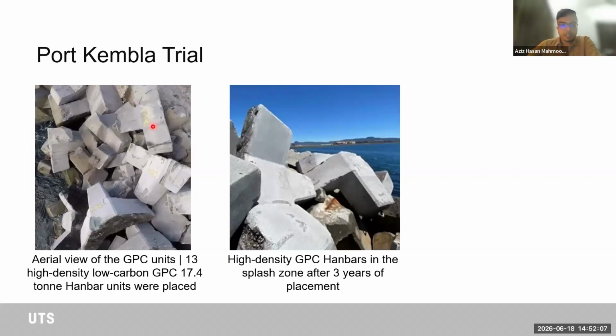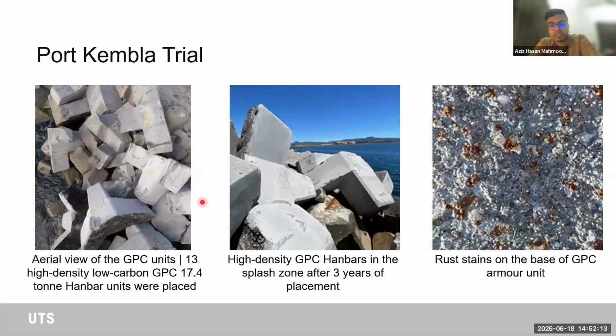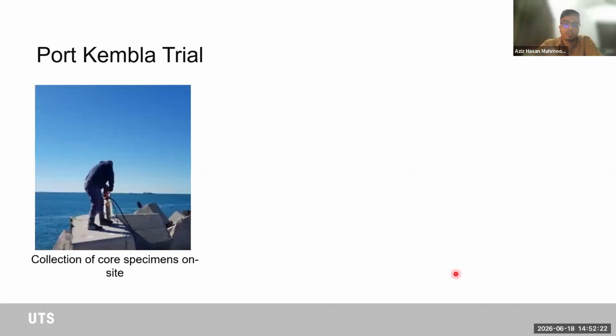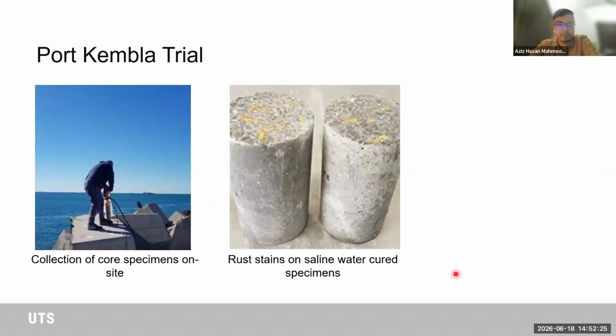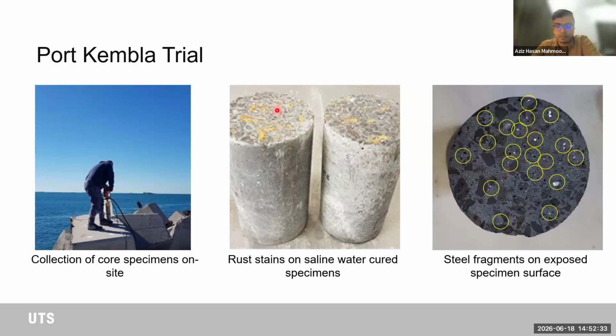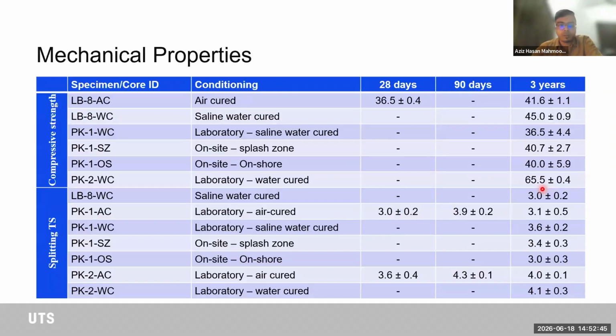So after 3 years, we went back to collect some core samples and to have a visual observation. So the first thing that we noticed was rust stains on the base of the GPC, on the geopolymer concrete armor unit. So we took some cores from the site, and we could see the rust stains on the specimens that were collected from the splash zone of the breakwaters. And after grinding the top bit and the bottom bit, we could notice steel fragments on the exposed specimen surface there.